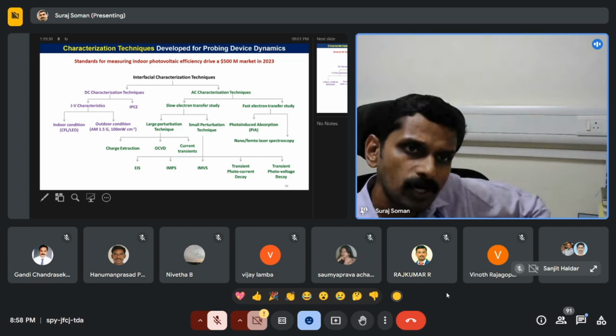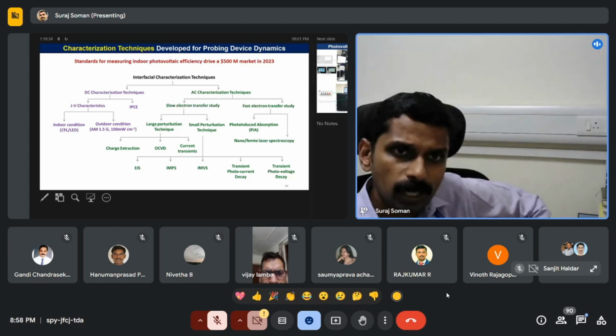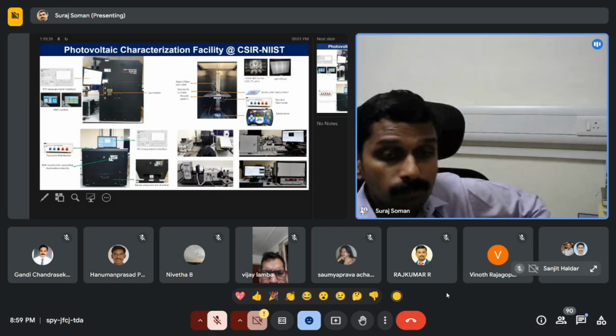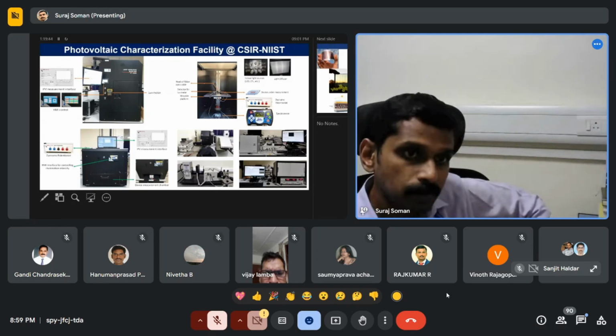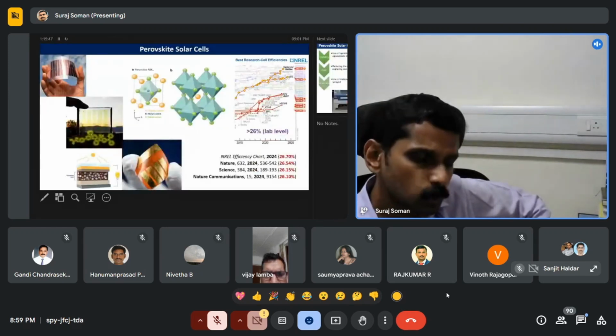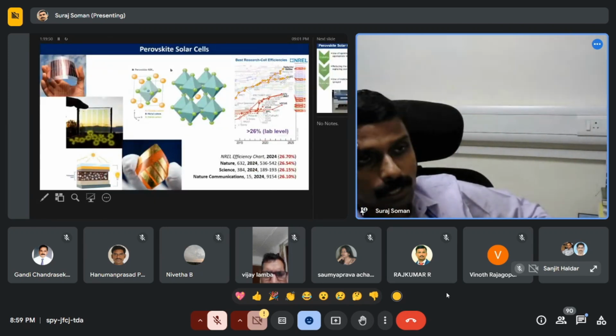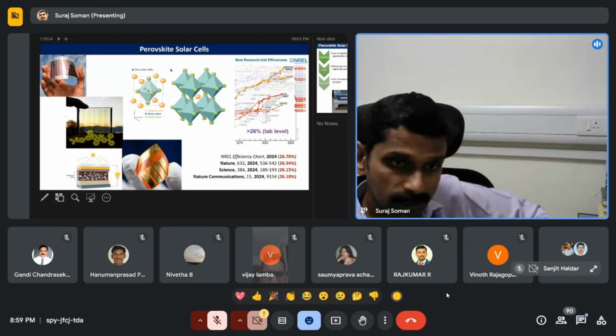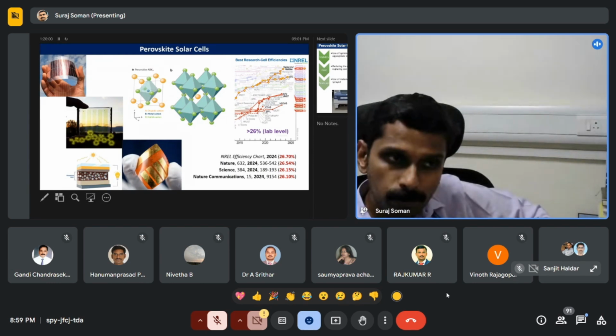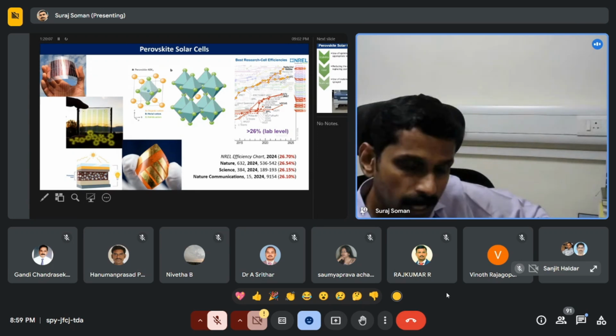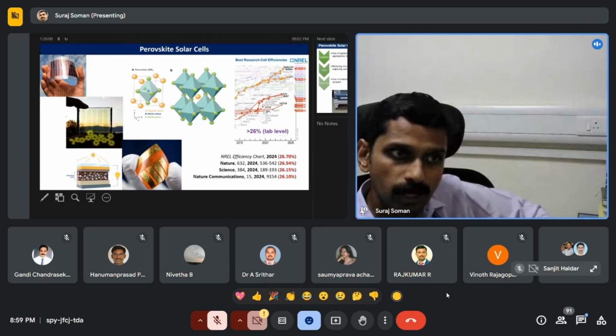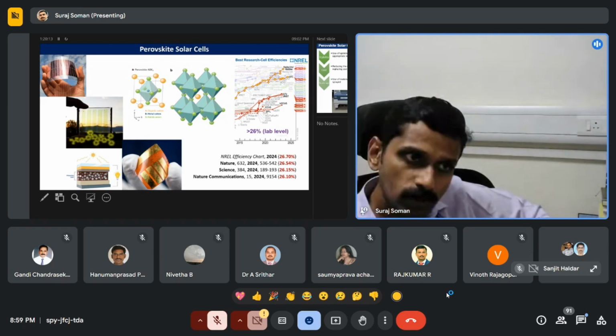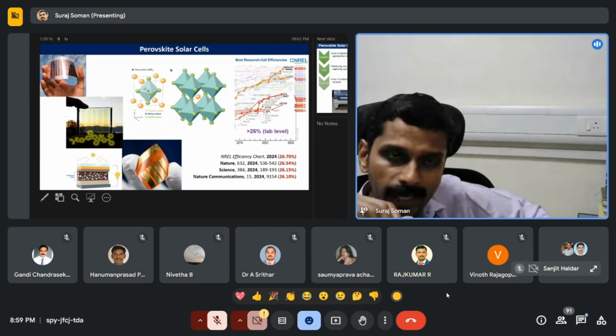We have come up with very unique electrical and optical perturbation tools optimized for studying these devices in more detail, and standard protocols for the measurements. And this is not restricted to the dye-sensitized solar cell, because, as many of you may be aware, the perovskite solar cell is an offshoot of the dye-sensitized solar cell. Here, instead of the dye molecules, you are using an organic-inorganic hybrid material, a perovskite material, with a general formula of ABX3. A is an organic cation, B is a metal cation, and X is a halide ion. You can change these metals, organic cations and halides, and tune the band gap.